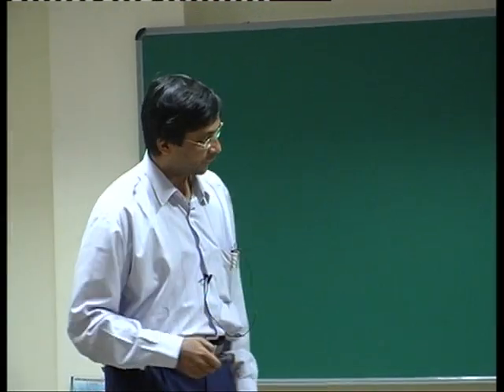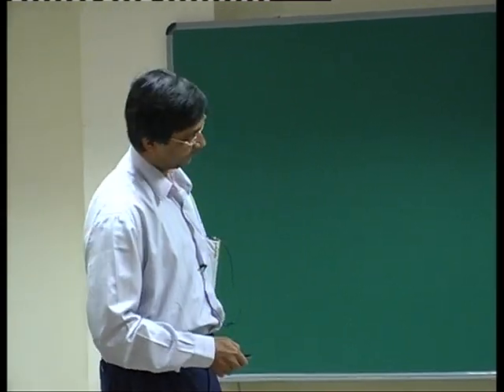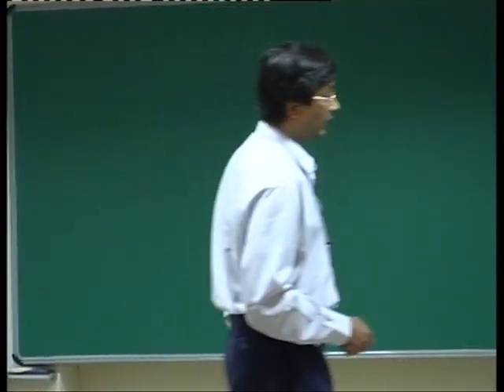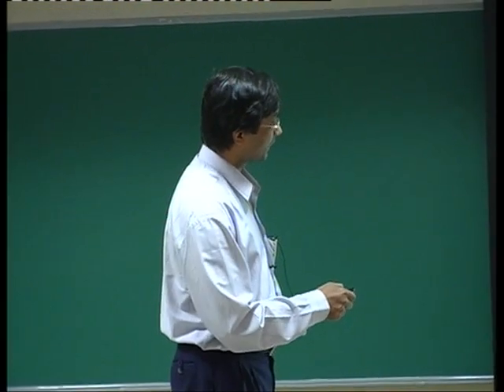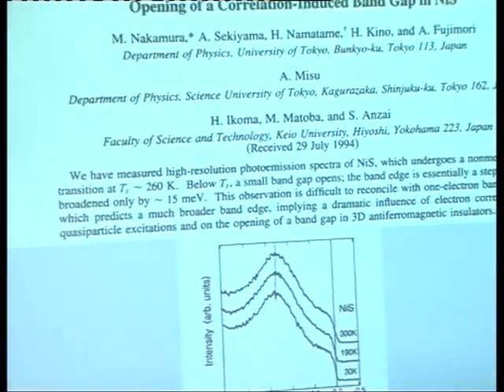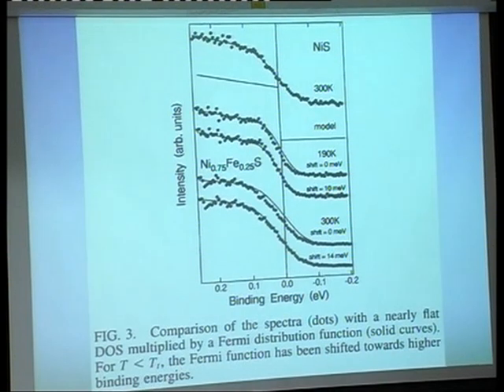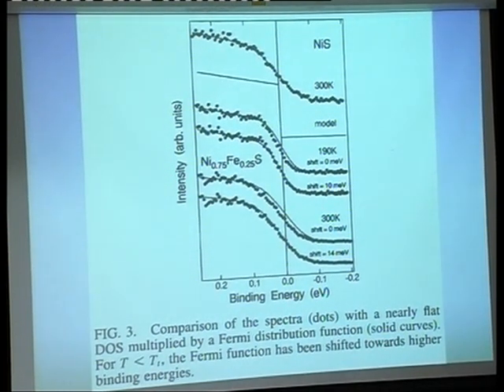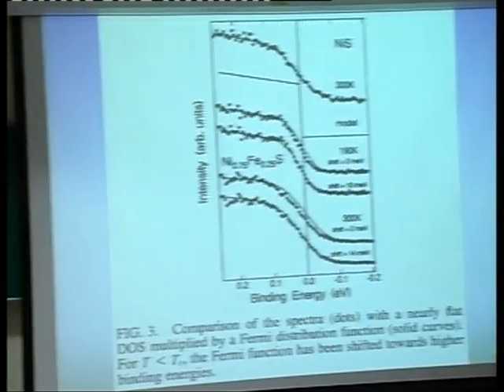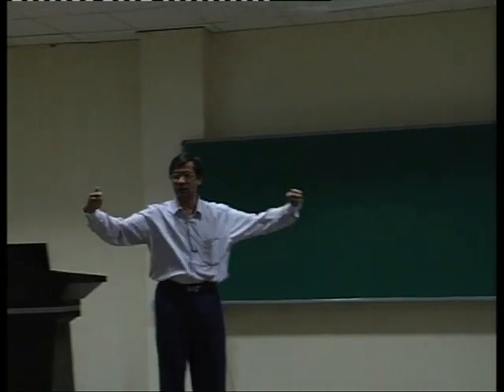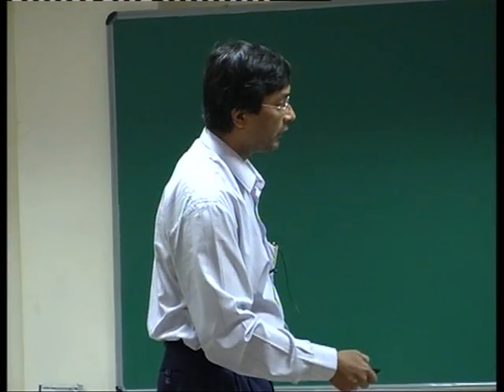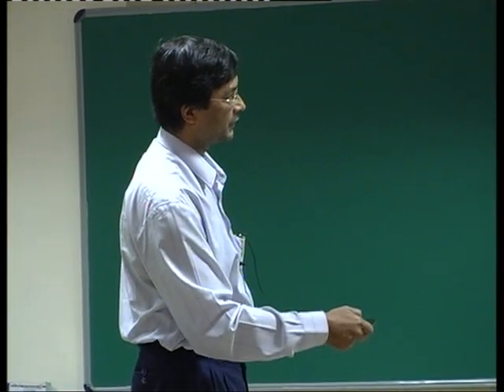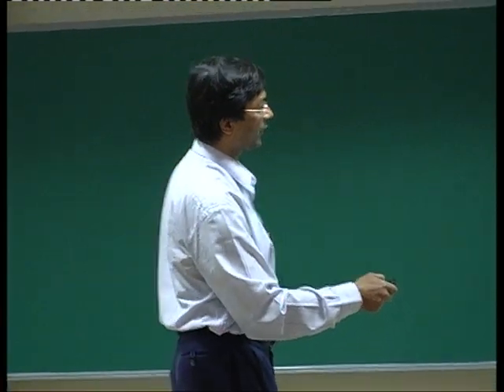And then of course Fujimori went and looked at very close to the Fermi energy too, and the data are shown over here. The dots are the experimental data. You can see in the previous view graph you had 2.5 electron volt, about 3 electron volt spread, but now you have a spread of only about 0.45 electron volt, 450 milli electron volt. So we're really stretching out so that we can see very carefully what's going on right at the Fermi energy. And this is the experimental data at 300 Kelvin.